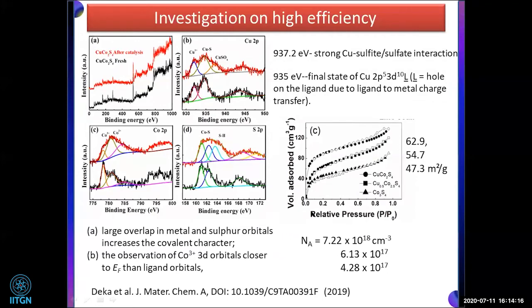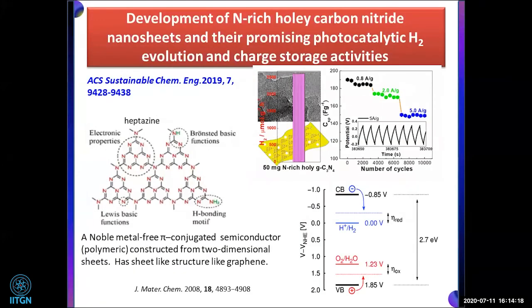So continue with that one. We tried this one, graphitic carbon nitride material, and we know well about the graphite carbon nitride material. This is made from the heptazine ring, and we have the C3N4 material, and this band gap is very good here, 2.7 electron volt, very much lower than the hydrogen evolution and very much higher than the oxygen evolution here. And it is a noble metal free pi conjugated semiconductor, and it is very low cost.